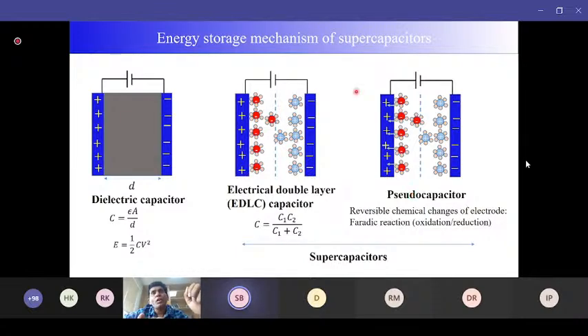And the pseudo capacitor is also a supercapacitor, but here the mechanism is a bit different. The same thing happens: negative charge goes towards the positive plate, and positive charge goes to the negative plate, but additionally there is a charge injection from these ions to the electrode. In the EDLC case, there is no charge injection. This is just the adsorption of ions, with no charge transfer between the ions and the electrodes. However, in the pseudo capacitor there is additional charge transfer between the ions and the electrodes. As a result, the energy storage performance of pseudo capacitive materials is higher than the electrical double layer type. However, they are much slower.